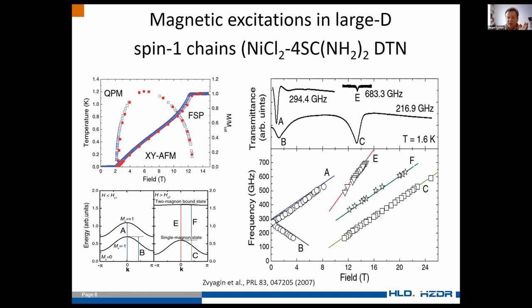So we studied the excitation spectrum above 12 Tesla. You can see that above 12 Tesla, we observe a number of excitations. And just by making a fit of this excitation spectrum, we were able to extract very important spin Hamiltonian parameters. And using these spin Hamiltonian parameters, we were able to describe the phase diagram, including the magnetization. And this is actually a transition from the quantum paramagnetic to ordered state. And this phase diagram was calculated quite precisely using these parameters, which we obtained from high field ESR.